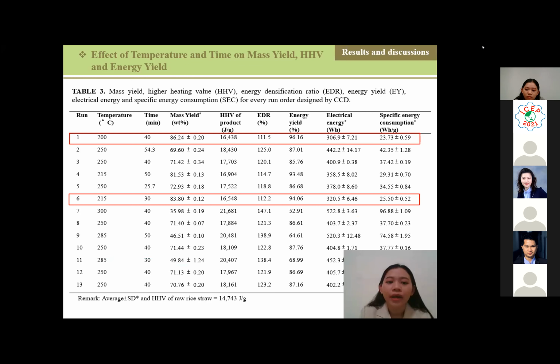As seen in the table, the energy densification ratio rose from 111.5% to 147.1% when the temperature was increased from 200 to 300 degrees Celsius for 40 minutes reaction time. This indicated that the quality of rice straw was improved by 11.5% to 47.1%. The energy yield of torrefied rice straw ranged from 52.91% to 96.16%. It was obvious that higher temperature results in lower energy yield. The decrease can be explained by the thermal decomposition of rice straw.